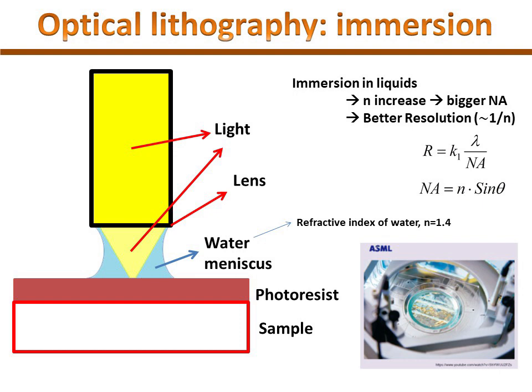The index of refraction of water is around 1.4, and this index depends on the purity of the water. The lithographic technique which uses water as a surrounding medium is called immersion lithography, and is used with UV light and also with EUV light. Immersion lithography enhances the numerical aperture, increasing the resolution, but at the same time decreasing the depth of focus. This last unwanted effect could be overcome using a thinner photoresist.